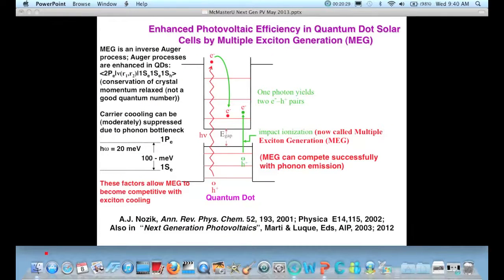So this was the idea. It was first proposed in 2000 or so, that in a quantum dot you slow down the cooling, which is the electron-phonon scattering, by having discrete states that arise because of quantization in the quantum dot, which typically, as I say, is between 1 and 2 nanometers.